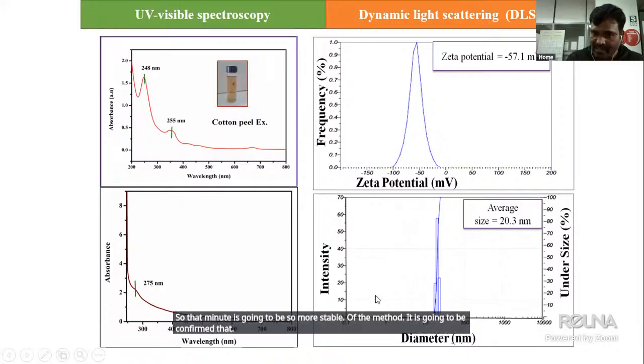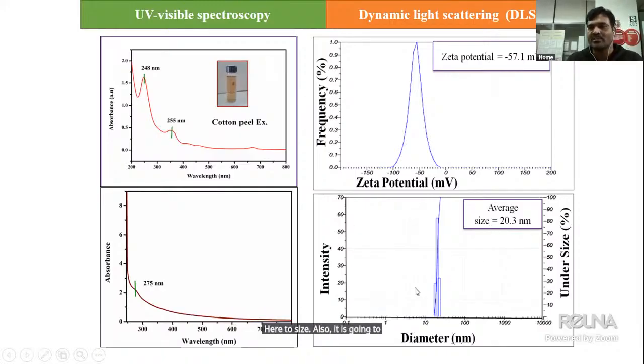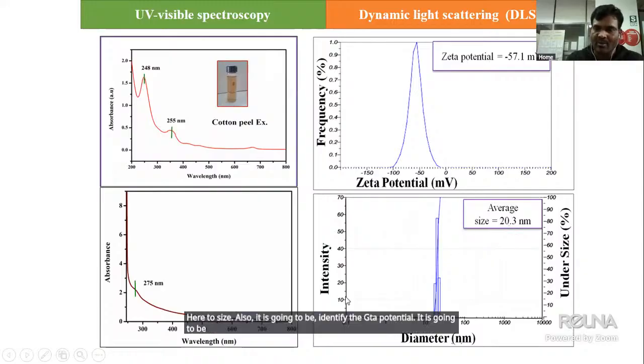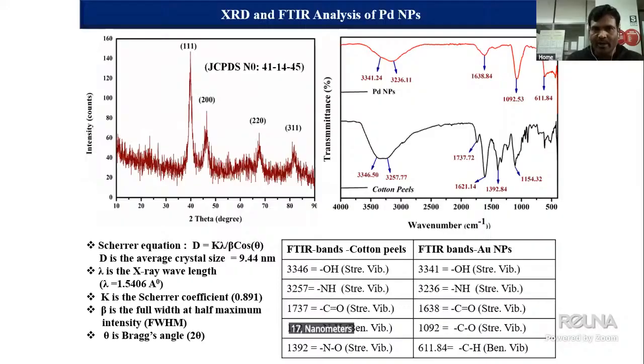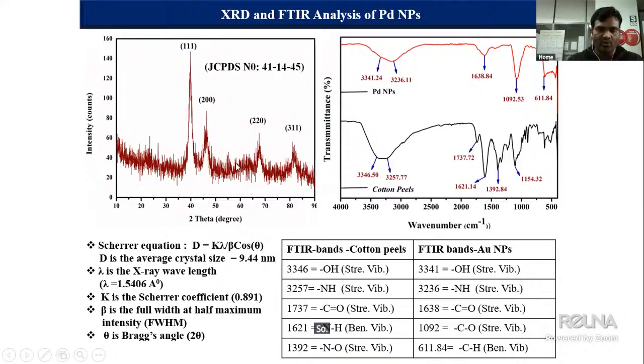Here the size is also identified along with the zeta potential. The average size of the material is 20 nanometers. Further, we identify the XRD and FTIR also. The XRD pattern shows clear multiple planes corresponding to the measurements. The synthesized material is confirmed by the JCPDS card number. The average crystalline size was calculated using the Scherrer equation, D equal to 9.44 nanometers.